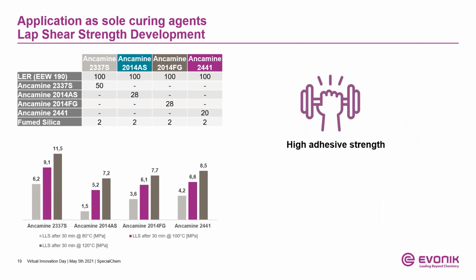Further, taking a look at the achieved lap shear strengths after curing at different temperatures in the range of like 80 to 120 centigrade for 30 minutes each, they clearly show that Ancamine 2337 offers the best performance with remarkable lap shear strengths, even at 80 centigrade curing, which already indicates good capabilities for fast green strength buildup. This is followed by the Ancamine 2441 and the Ancamine 2014 grades.